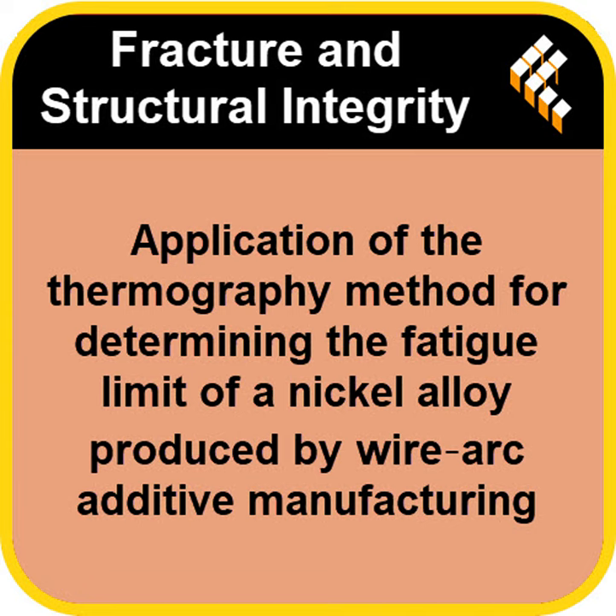It is. When a material is cyclically stressed below its true fatigue limit, the energy it dissipates internally is tiny, almost negligible. But the second that stress amplitude goes over that critical limit, the damaging process kicks in. We're talking microcracks starting to form, dislocations moving, and all that activity releases a measurable amount of energy. And that energy release is converted directly into a rise in temperature on the surface.